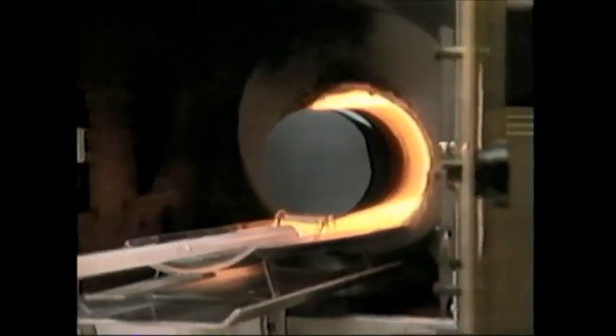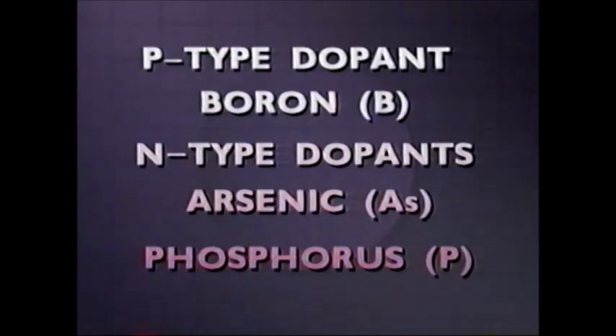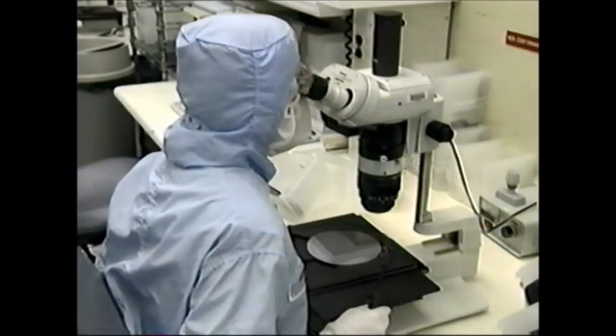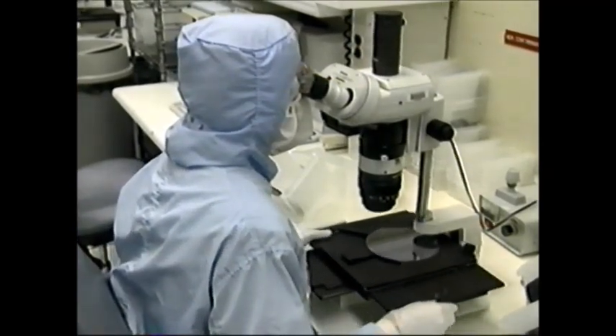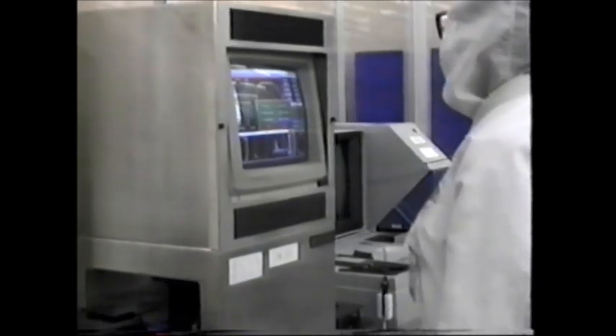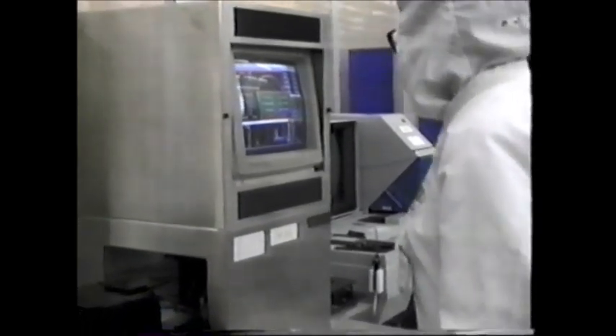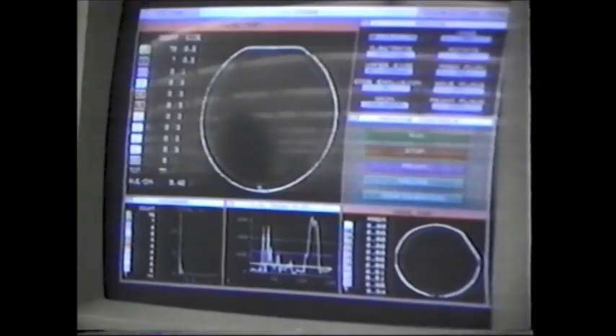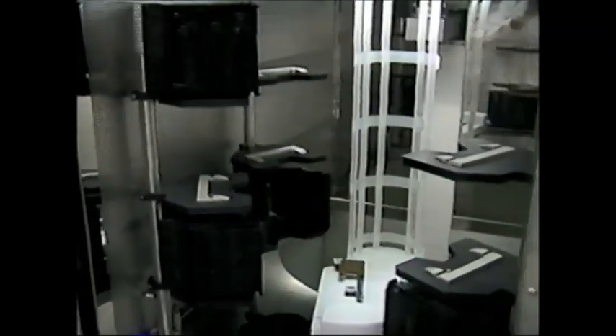Finally, the wafers are heated for a short time to anneal the surface back to a monocrystalline state. P-type dopants may be diffused into wafer surfaces using boron, and N-type surfaces are formed using phosphorus or arsenic. As in other steps, these elements are available in carrier gases. Quality control is performed after each processing step. One such quality control test for surface faults involves reflecting a light beam off the surface of the wafer and analyzing the reflected light. Diffusion can be accomplished using solid or gaseous dopants at various temperatures and pressures.